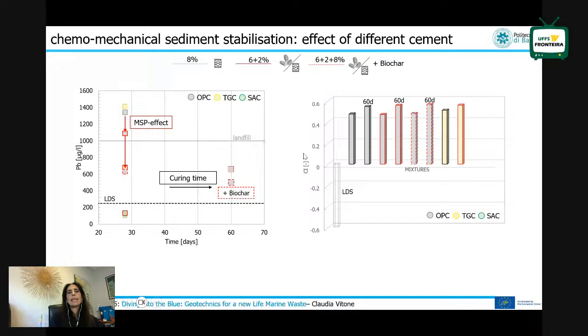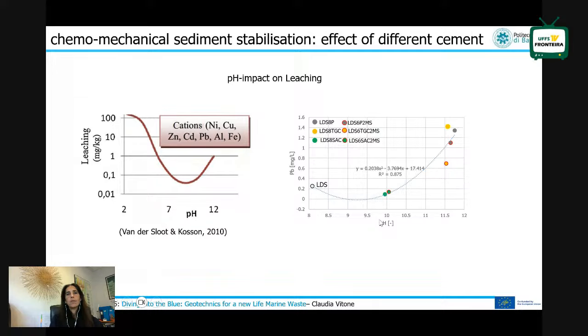The consistency index of the different cements is again showing that the behavior is practically almost similar. The only cement that is not working very well is the sulfoaluminate, because, as I mentioned, the sulfoaluminate is not performing very well in terms of mechanics, probably due to the presence of a lot of sulfate within the mix design of the cement. But on the other side, we can see that the sulfoaluminate cement is performing very well in absorbing the pollution. If we plot the lead versus the pH, we have a quite common trend that is already recorded in the literature, with essentially higher efficacy for pH that are about 10.